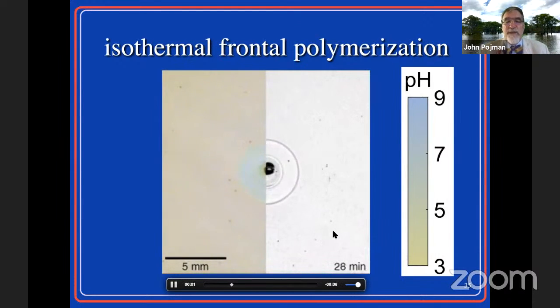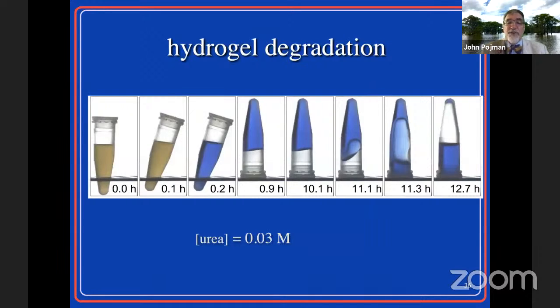To be commercially useful, we have to find a way to make it so that we can store it this way. We want to have a very long shelf life. This system, once you mix it up, after a few hours, it's going to react anyway. So having a front is not such a clear advantage. But it's also possible to, by changing the final pH, you can get hydrogel degradation. So you get a system that turns into a gel, and then over hours, it will degrade.